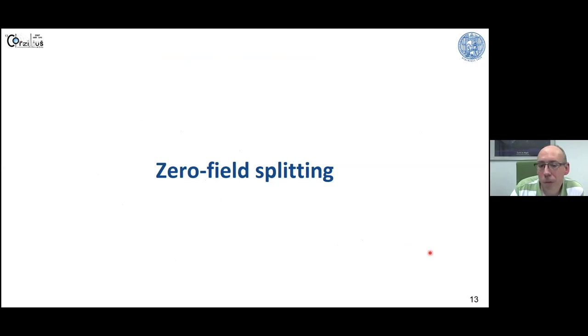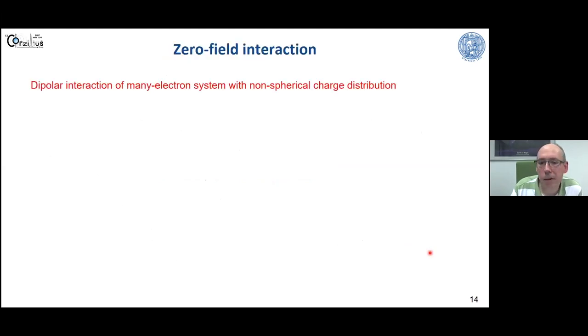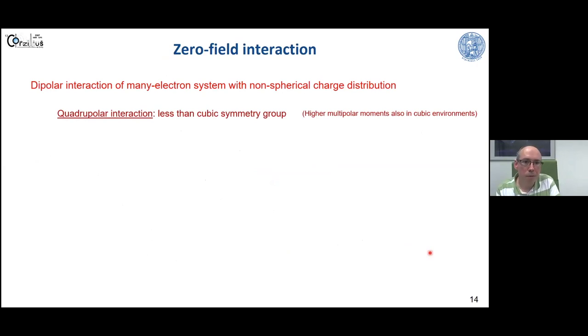Now for a couple of minutes, let's talk about zero field splitting. Then we have a short break. So the zero field interaction is the dipolar interaction of a many electron system with a non-spherical charge distribution. That means if we look at a quadrupolar interaction, we can only observe this if the symmetry group of our system is less than cubic, for example, tetragonal or orthorhombic. Then we can observe a quadrupolar contribution of the zero field interaction, let's put it like this. But there might also be higher multipolar moments in even cubic environments, but these are usually not observed so much in most systems.